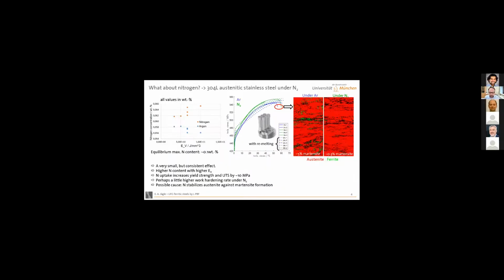First thing that we did was we looked at a very simple austenitic stainless steel processed under argon and nitrogen. And I have to tell you, the differences are there, but you have to look very closely to find a difference. The higher the energy density, the higher the nitrogen content becomes if you process under nitrogen. It's the reverse when you process under argon. But if you look at the numbers, these are very small differences.